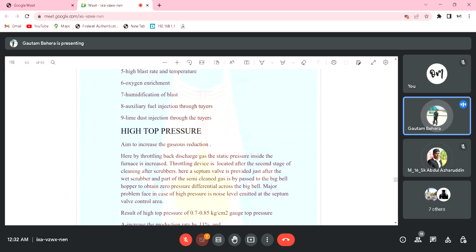Obviously, in the first case 10 people are holding the same amount of load. Now I am reducing it to 8. Okay, fine, it is again fine. But if suddenly I reduce it to 5 people, the same load, what will happen? They all will collapse. The same thing happens to the coke. If you reduce the amount of coke to a large extent, then that amount of coke may collapse. They may become fines. So there will be no permeability in the bosh region, right?